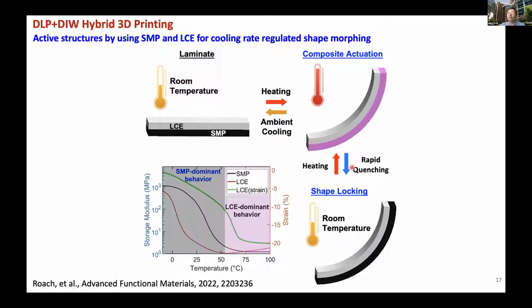But if I do ambient cooling, if I heat it up and cool it down slowly and gradually, the LCE would drive things back to the original shape. But if I do a quenching, I just quickly cool it down. In this case, the SMP will immediately become stiff, while the LCE does not have enough time to do this kind of phase transition. So we can actually lock the shape into the high temperature shape. As I heat it up again, it will become this shape again.